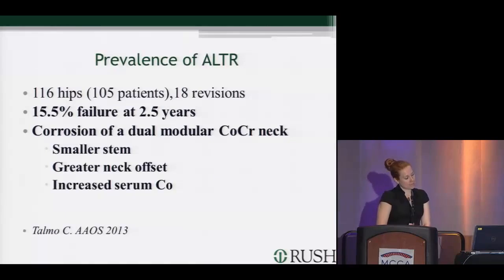Recently, data has been reported on the prevalence of adverse local tissue response. A 15.5% failure rate at 2.5 years was recently reported by Talmo et al. This was associated with the corrosion of the dual modular cobalt chrome necks, and this corrosion was then associated with a smaller stem size, greater neck offset, and increased serum cobalt levels.